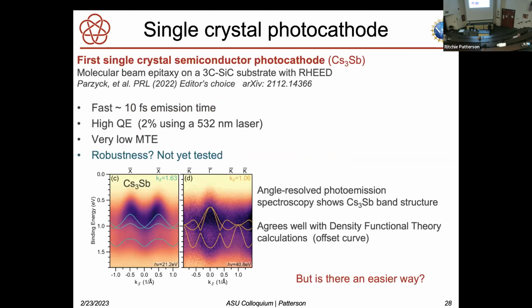So one solution is to grow a single crystal photocathode, and in fact, just this past year, that was achieved for the first time, a single crystal semiconductor photocathode with molecular beam epitaxy, and it looks very promising. It's fast, it has high quantum efficiency and low MTE. We don't know about robustness yet. There's work going on to cap photocathodes with graphene layers that looks very promising. In fact, some of that work was done here. So this looks promising, but it's sort of a Maserati of photocathodes, and that makes you wonder, is there an easier way?